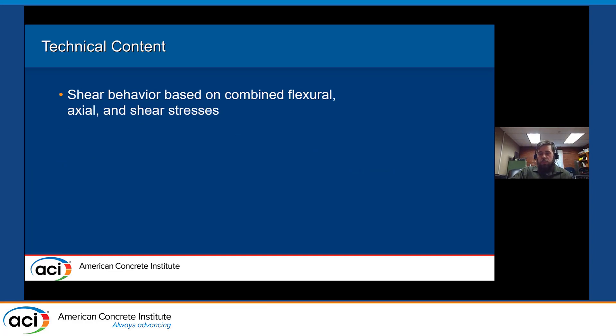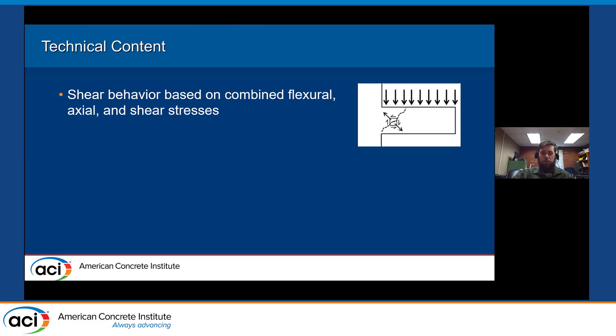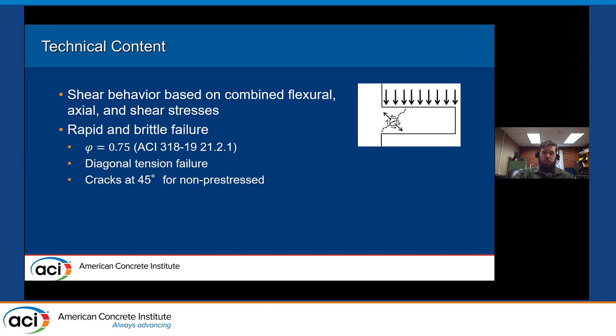In terms of a short summary of the technical content on shear behavior: shear behavior in a concrete beam is really a combination of flexural, axial, and shear stresses acting together on a beam. Looking at a cantilever beam, those stresses cause principal stresses that create tension — tension and concrete are not friends — so we get a diagonal tension failure that's rapid and very brittle, which is not what we typically want. We use a smaller phi factor for shear of 0.75, and for non-prestressed elements, cracks occur at a 45-degree angle based on those principal stresses.